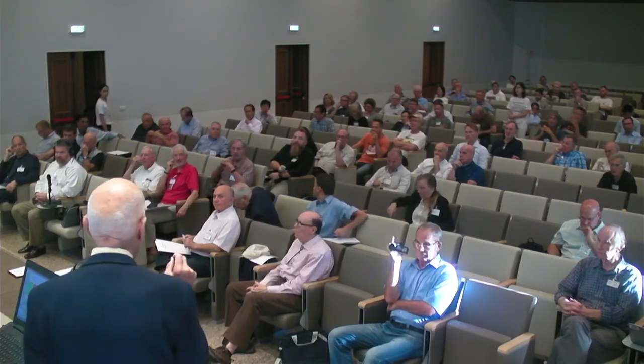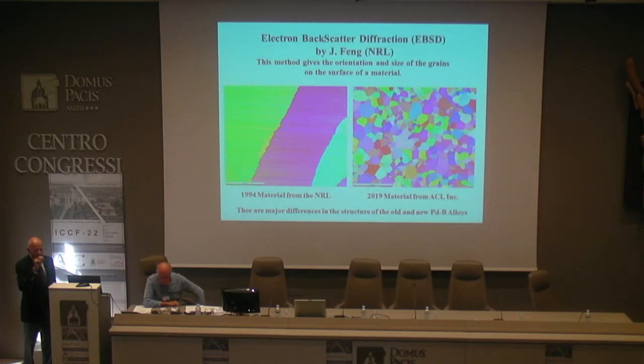Yeah, I appreciate that comment. We have measured, for galvanostatic conditions, the variation in the voltage due to bubbles. If you apply a voltage and have a bubble on the surface, there's a dip in the current. We have seen that in some nickel hydrogen runs. It's been analyzed by a colleague of mine in Switzerland, and we know that, but I don't know a way to stop it. So I'm going to want to talk to you in detail about how to do that, because clearly the bubbles are good news and bad news. The good news is they stir the electrolyte and lead to isothermal conditions inside the test tube, but they do block the cathode. So thank you.